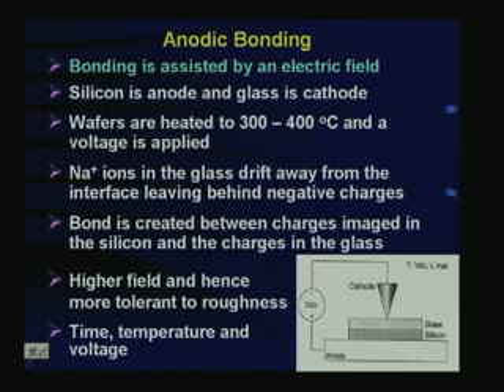Now, we are switching over to the anodic bonding technique, which is much more promising in case of MEMS wafer bonding. This particular technique is assisted by an electric field. Till anodic bonding, in earlier bonding techniques we never used any electric field. Now, here you require some electric field. In the bottom you can see a pictorial diagram of the anodic bonding technique. So, here silicon and glass bonding is shown. Silicon is used as an anode, you can see in the picture, and glass is used as a cathode. These wafers are kept on a heater whose temperature is raised within 300 to 400 degrees C and voltage is applied.